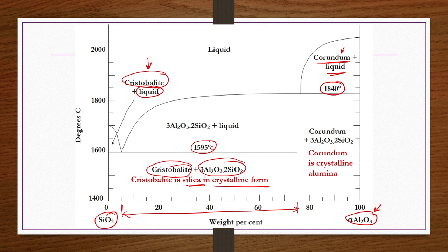However, if you don't want any crystalline silica, you need a liquid sample, so you further increase the temperature. Within the same composition range, you still get mullite and then liquid within this envelope, where the composition varies between 10 to 75% of alumina and silica, right. But if you have almost pure alumina, then corundum and mullite; here also you get mullite up to the temperature of 1840 degrees centigrade.